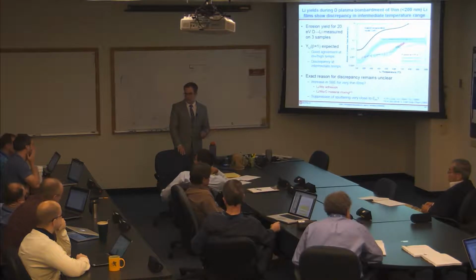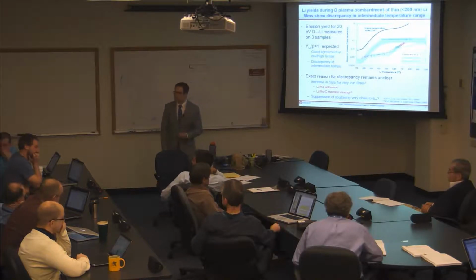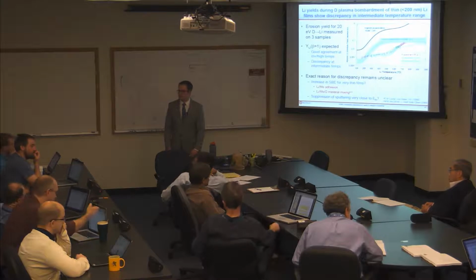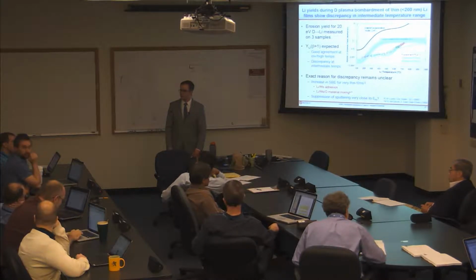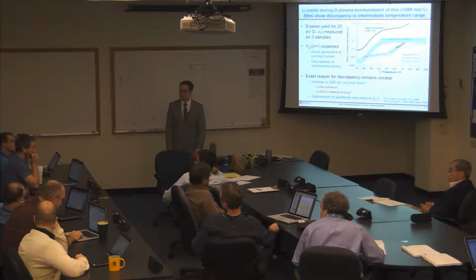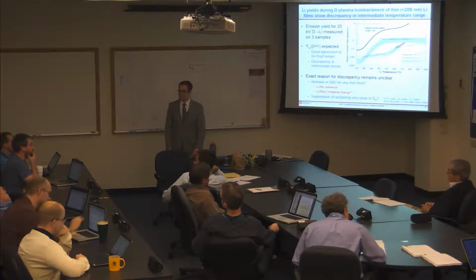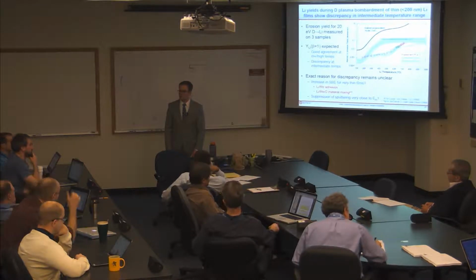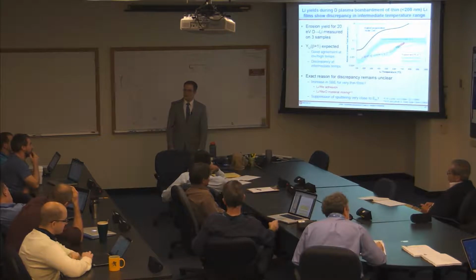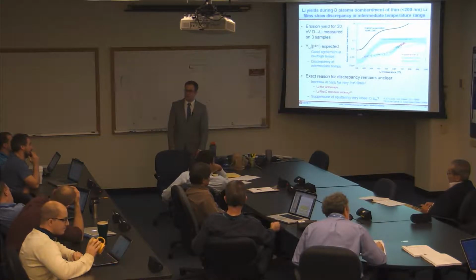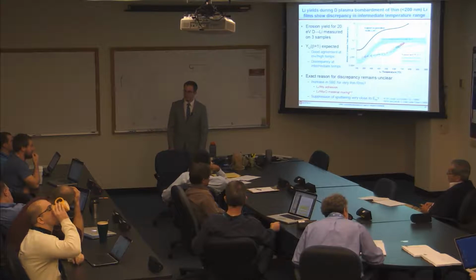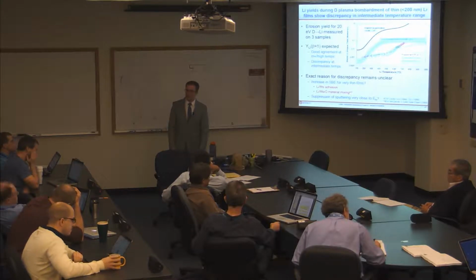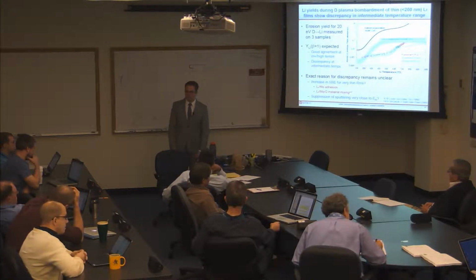Would you expect to see oxygen emission if it was lithium oxide? Is it possible that the oxygen and lithium could become unbound, but the oxygen doesn't become unbound from the sample? Is there any reason to assume that might happen? I would think the oxygen would be dissociated pretty quickly at the densities and temperatures we're talking about. But we did also look for hydroxide emission, which is around 308 to 310 nanometers, and we didn't really see any of that either.